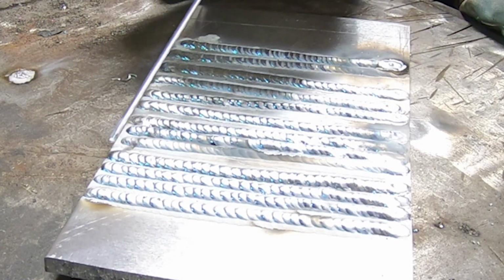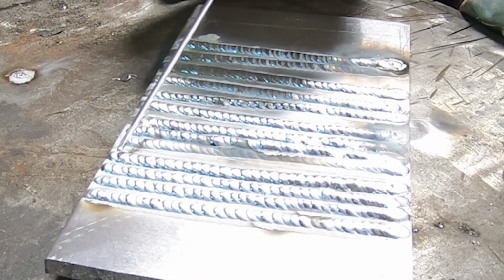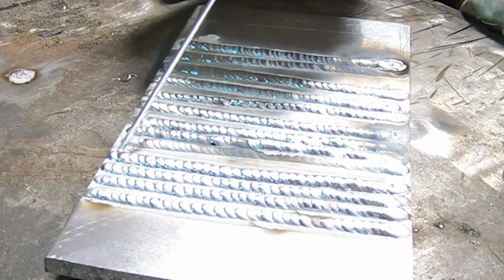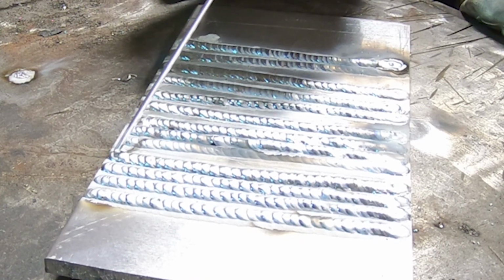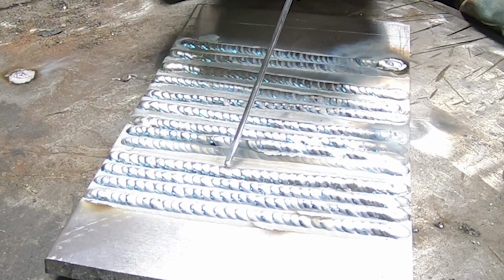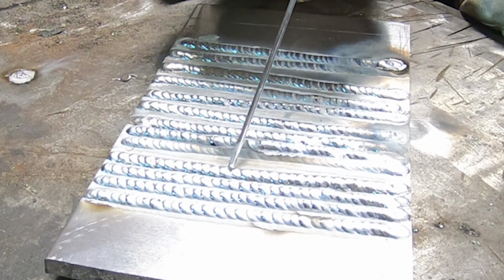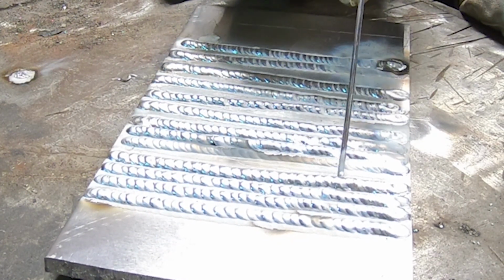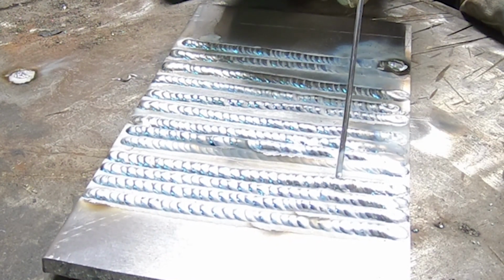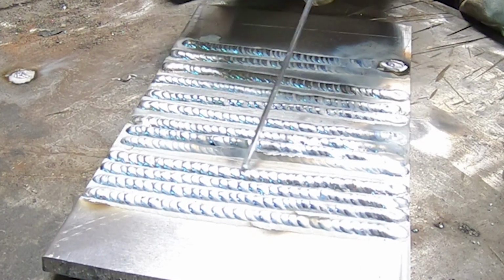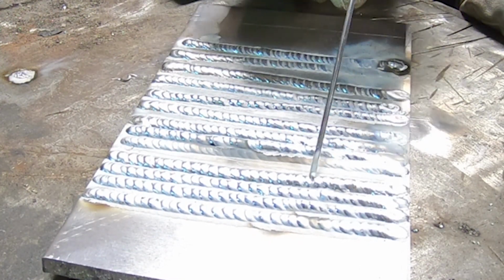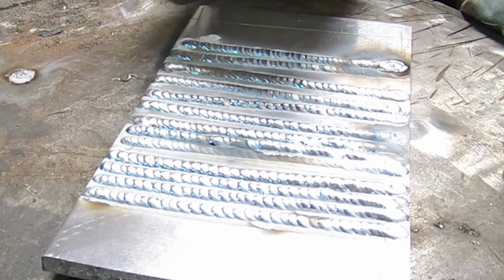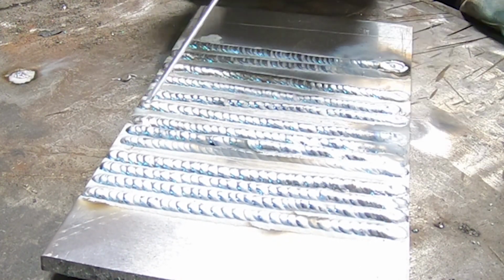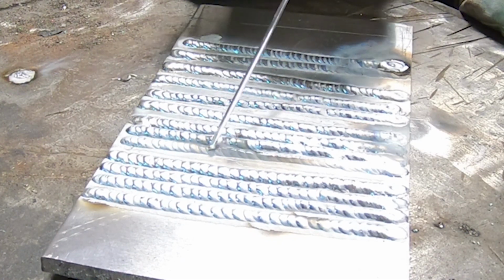So that's never good. And then this bead right here is actually the best one, I think, out of everything tonight so far. Very consistent, except for that dab was a little big. And then we got down, and we probably could have used a little bit more heat right here, but overall looks-wise and penetration-wise, the fourth one we did is probably the best. This one is now covered by soot because I kept dabbing the tungsten. This was the first one with the bald electrode, and it was terrible.